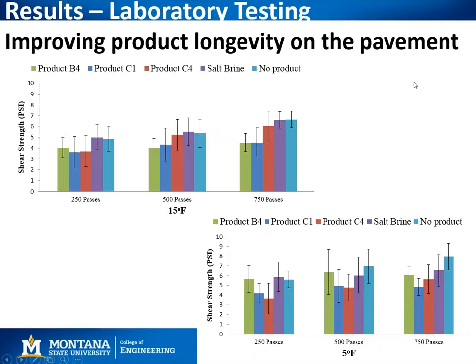So to further investigate this, we looked at how these products improve longevity on the pavement. This was mentioned as one of the benefits of the agro-based products from the survey respondents. So we used those same test methods where we had the pavement sample, we applied the product, we compacted the snow on top of it, and then we trafficked it for 250, 500, and 750 passes. And then we measured the bonds, or the shear strength, that are required to move that patch of snow or plow that snow off the pavement for these 4 products.